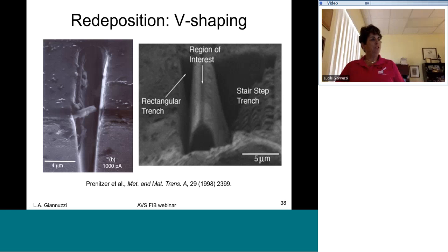This redeposition is also attributed to V-shaping, both in milling trenches as well as milling TEM samples. So, for example, if you're trying to mill a hole into a feature, this hole will always result in this V-shaping. The amount of V-shaping is going to depend on what kind of beam current you're using and what kind of material you're cutting into. If you're making a TEM sample, this will result in sort of an opposite V, where the sample's thicker at the bottom than it is at the top. And this is why, in some cases, we always tilt into our sample. When we're making TEM samples, we'll tilt into it plus or minus 1 degree or 2 degrees.